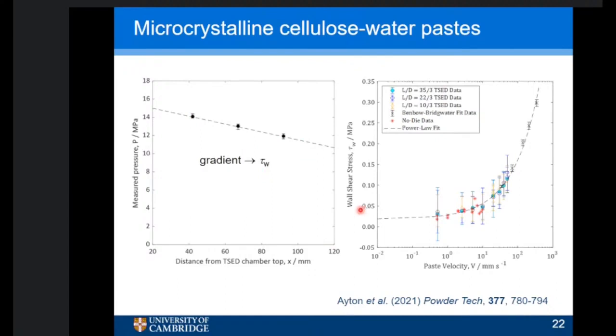And then I need to point out that this is not for a tungsten carbide paste. This is for a microcrystalline cellulose-water paste. This is a pharmaceutical material. Now, the reason why you're not seeing tungsten carbide paste results is because they're confidential to the company. So another reason why we do things with soap flakes is because we can publish those quite happily, and the microcrystalline cellulose work we can publish quite happily, but the company-specific material, obviously the company hold on to those.